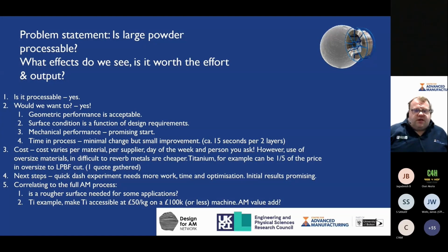In terms of cost, quite a few words there, but the hard hitting answer is titanium in laser powder bed cut versus an oversized titanium. I've only got one quote, but I got one quote to do a quick check, and the oversized titanium was a fifth of the price. So if we could create parameters that allow us to push that, can we potentially add value by using low cost but high value materials like titanium on a low cost machine like the Xact Metal XM200C? Can we really start to add value? And I say we certainly can.